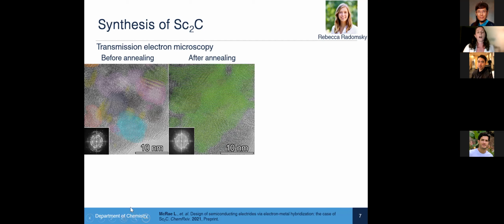And so on the left image before annealing, you can see there are many small crystals, and the Fourier transform associated with this image shows more of a ring pattern, whereas after annealing, we see one very large crystal domain, and the Fourier transform shows a spot diffraction pattern, again supporting that we have very large crystals.